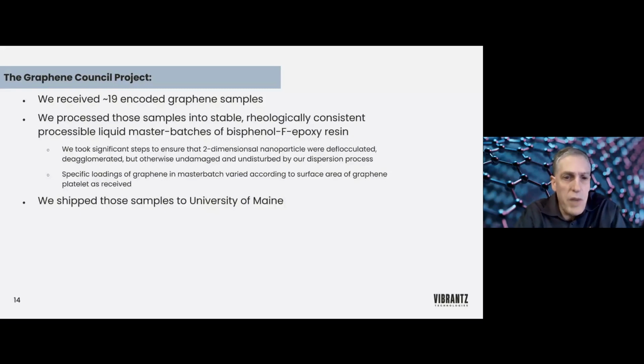We also made specific loadings that would vary according to the surface area the graphene platelet has, in order to make sure that we had a stable dispersion first of all, and secondly, one that the University of Maine would be able to handle. And once we had processed these samples to rather stringent specifications, we shipped them to the University of Maine where they performed further testing. Next slide.